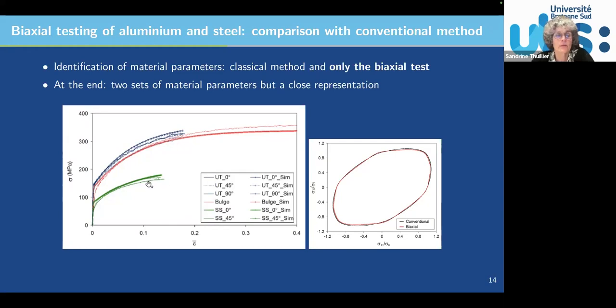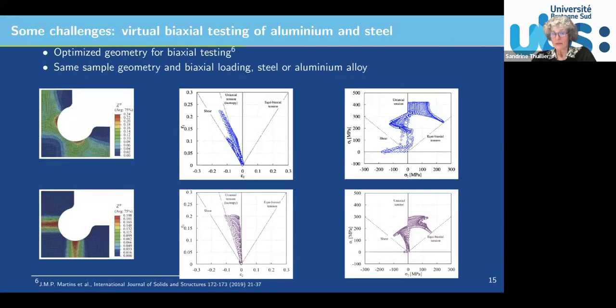And so you've got the thicker line for the experiment and the thinner one for the numerical simulation. And you can see that the agreement is quite good. So with one test you can reach a very good correlation with the prediction under monotonic loading. Sorry, not really monotonic, a homogeneous type test. Okay, so these were very encouraging results. So let's try to go on.